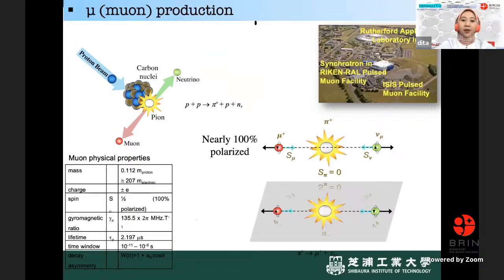Okay. So what is mu-SR? We need muon. So mu here is the abbreviation of muon. We can produce muon by using an accelerator. We need a proton beam, and the proton will hit the muon target. It's carbon nuclei, and it will produce pion, and the pion will quickly decay into muon. So muon is 100% polarized due to this nuclear reaction. Muon has mass, charge and spin. And muon is very sensitive, by which I mean that the gyromagnetic ratio is so large. So only a few Gauss of magnetic field can make the muon precess.